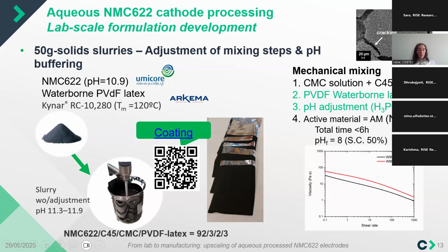Without the pH regulator, for instance, it's more evident that cracking and bubble formation occur. In this picture, there was bubbling due to hydrogen evolution from corrosion of the aluminum, which then led to cracking during the drying step.